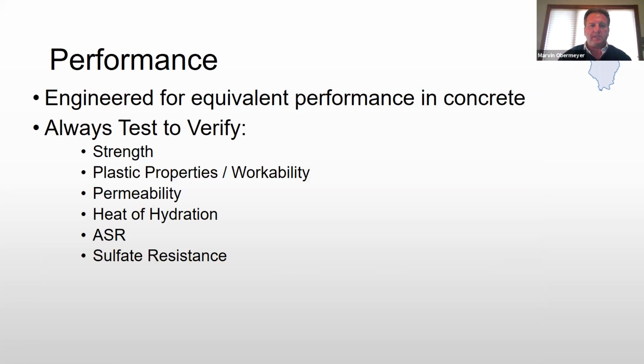All right, from a performance standpoint, it's engineered for equivalent performance. What that means is when our plants were making a type 1 cement and then they go to a type 1L, the goal there is that the 1L meets or exceeds the performance of the type 1. So now, obviously, as we roll these products out, I always encourage everyone to check your strengths and your plastic properties before and after. Usually it's beneficial for a lot of the other parameters, like permeability, because we have smaller particles here. Heat of hydration should be very similar, but obviously always check. Alkali silica reactivity should be very good, but always check. Sulfate resistance should be the same, if not better.